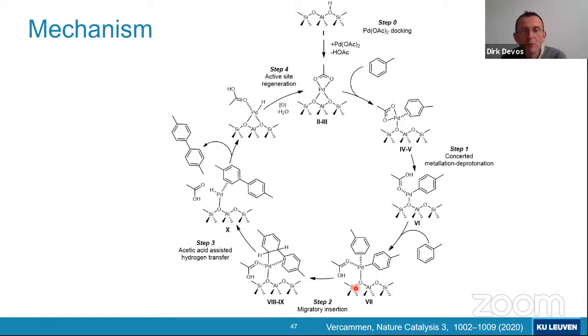And then the second step, of course, is one which is more hypothetical, but most computational evidence in fact points to an attack by this first tolyl ligand on the palladium on a second toluene molecule in a kind of migratory insertion, so that eventually you do have a bis-aryl compound which is made and which then leaves the catalyst, leaving the zeolite pores.